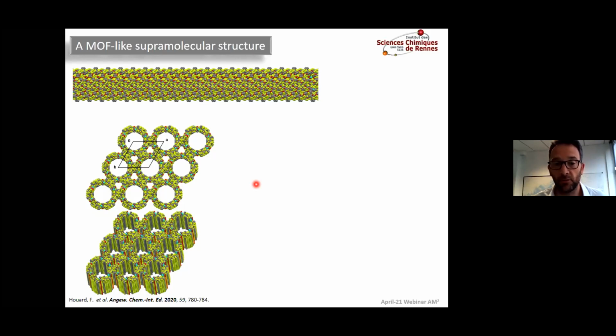It's very strange, and at the beginning we said, okay, maybe we can have a huge library of compounds, and it would also be very interesting from the magnetic point of view to be able to cut the chain with 10 units, 6 units, 4 units. We make a lot of chains in the crystallization conditions, and we always end with the 6. So maybe it's not, but we are not able to find another solution. As soon as you put enough water, you get the 6 every time. All right, perfect. Thank you.